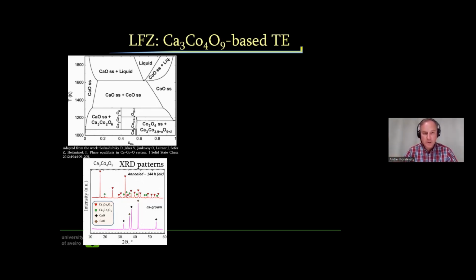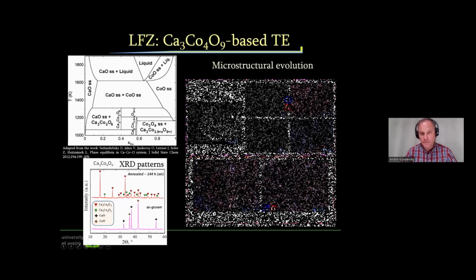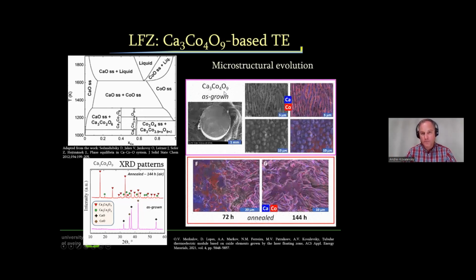So to turn this material into a thermoelectric one, we need to apply heat for a really long time, more than 100 hours, to eventually form this desired 349 phase, which forms in a very narrow range of concentrations and temperature. So you can see the microstructural evolution of such fibers, for example, as-grown fibers.